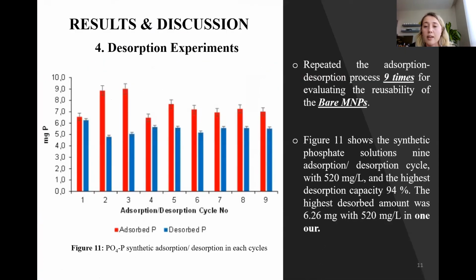Well, in the last slide, these desorption results were demonstrated in figure 11. Adsorption and desorption experiments were repeated 9 times for evaluating the reusability of bare magnetic nanoparticles and the recoverability of phosphate ions. And here you see in figure 11, well, the highest desorption capacity actually wasn't shown in this figure.